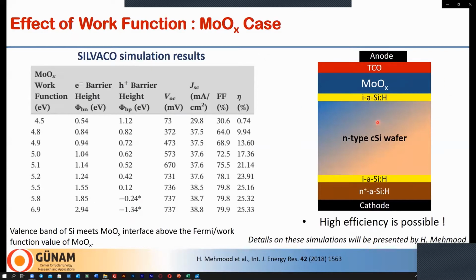For this structure, we placed molybdenum oxide on the front side, and the back side is composed of intrinsic and doped amorphous silicon. And the interface here is also passivated with intrinsic amorphous silicon. We use amorphous silicon, intrinsic and doped N-type, because the material properties are known, so we can isolate the effect of molybdenum oxide and its work function on the overall device. We have found that the solar cell parameters are very sensitive to the work function of molybdenum oxide, and that the cell efficiency increases with increasing that value.